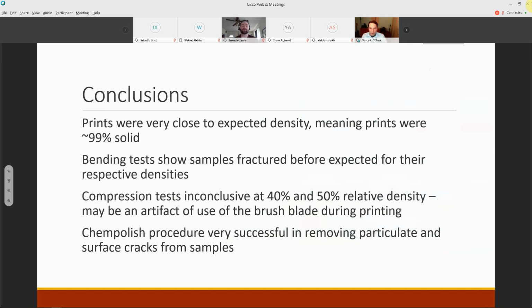Our bending test showed that our samples were fracturing before the expected for relative densities. So that is a bit of a concern as far as that property. Our compression tests were a bit inconclusive, especially since the 40 and 50% relative density tests seemed to be flipped from what you'd expect. So that may be an artifact of using the brush blade during printing or some other flaw in the print. And the chem polishing procedure was very successful in removing particulate and surface cracks from the samples. So we had a huge reduction in that surface particulate.